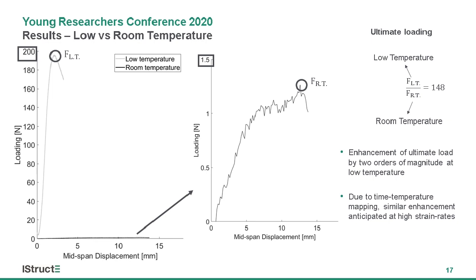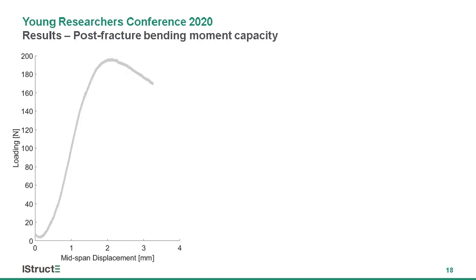Due to the time temperature dependency of the PVB, a similar enhancement is therefore anticipated at the high strain rates associated with typical blast loading. Based on experimental results from the low temperature bending test, analytical models were developed to describe the post-fracture bending moment capacity of laminated glass.